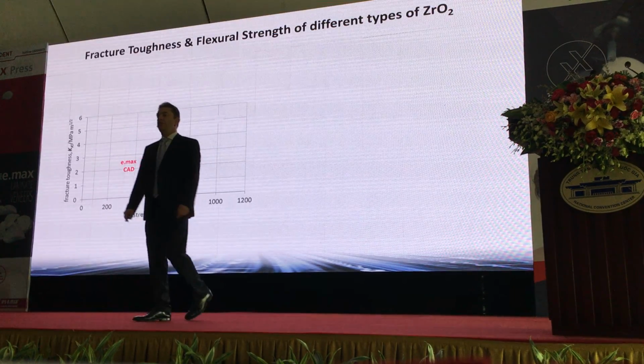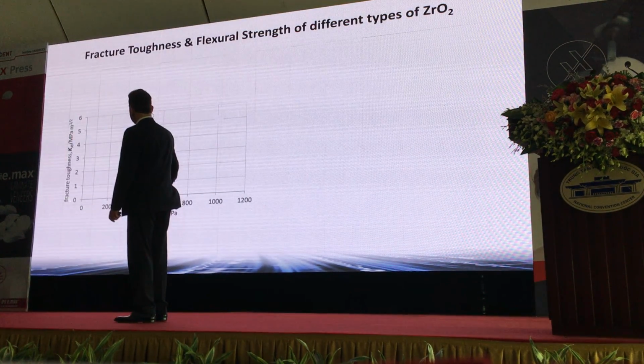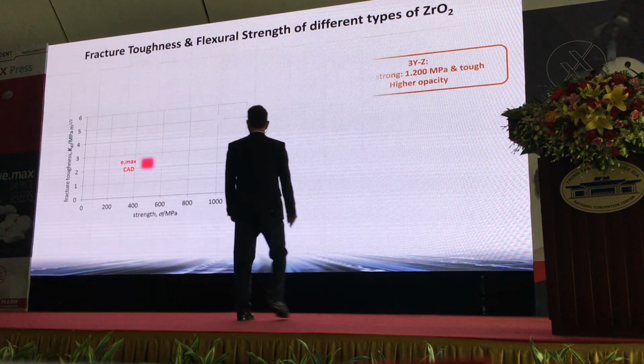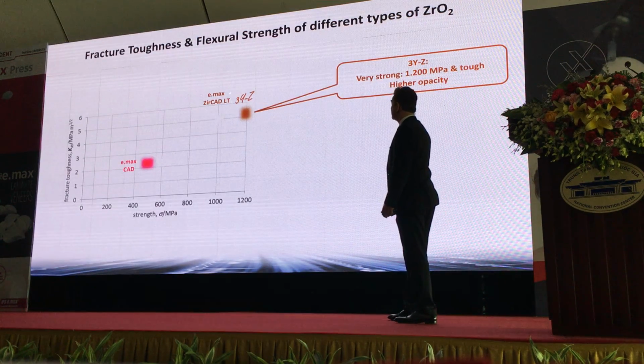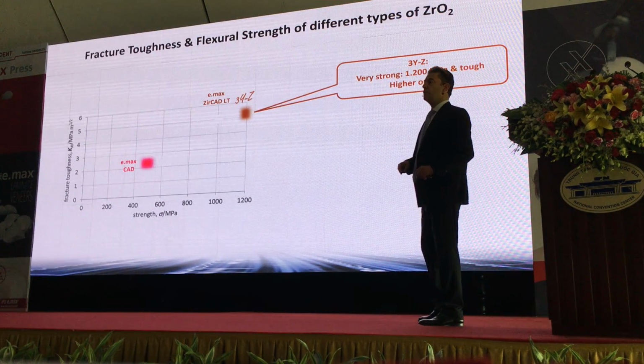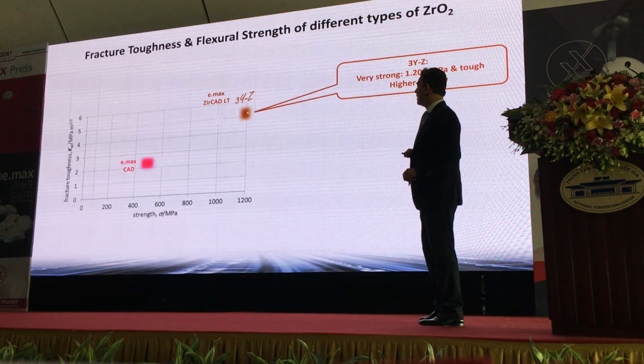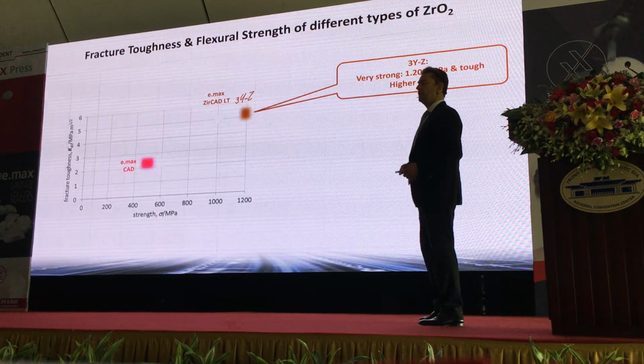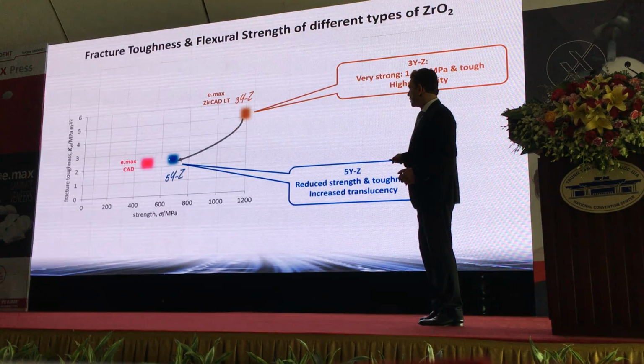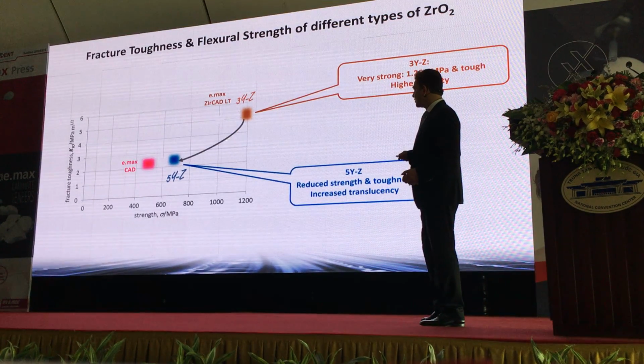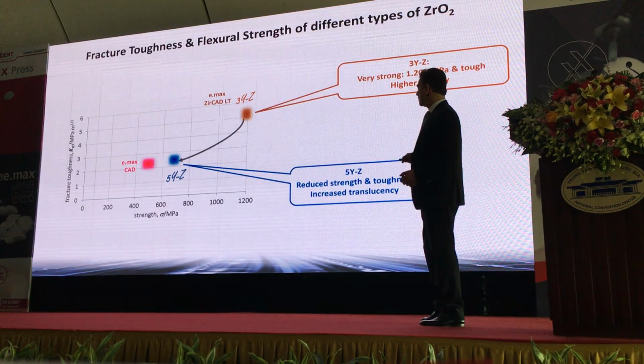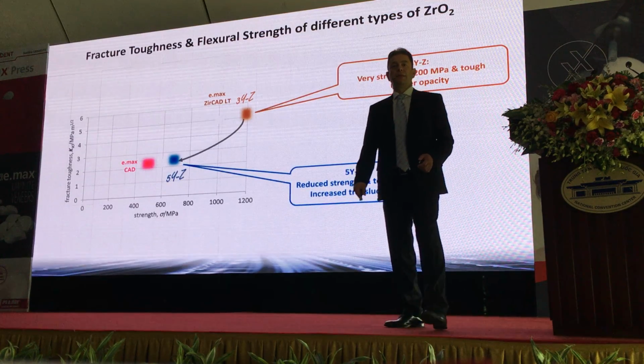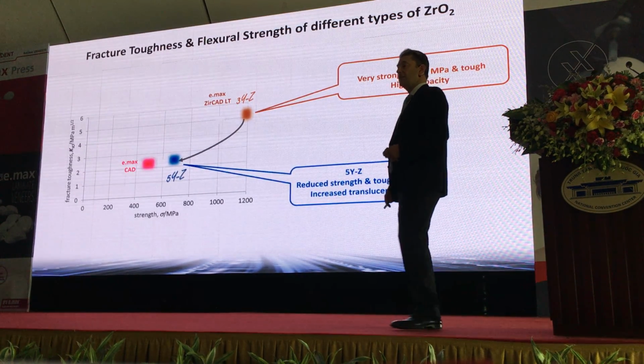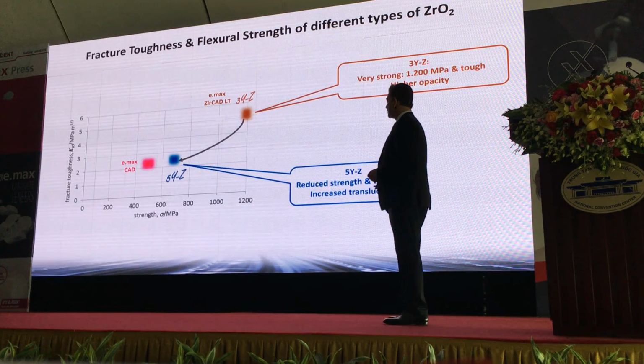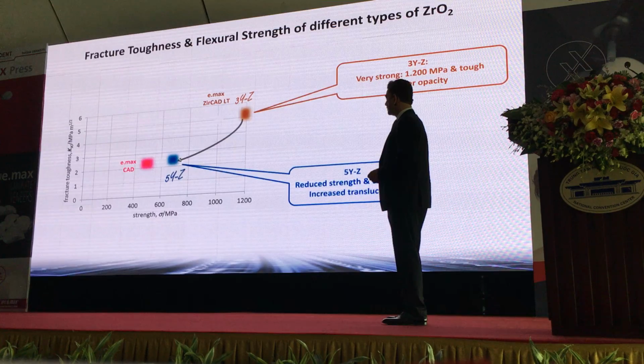All right, and you can see if we compare now the different zirconia to Emax, the original Emax lithium disilicate, we see this fracture toughness and flexural strength. So up here, this is the original, let's say, zirconia, the very strong zirconia, which is more opaque. So we have the very high flexural strength and fracture toughness. And if we really put a lot of yttrium oxide, much more than this one, the physical properties are decreasing. You can see, not so different from Emax. So these are the most translucent zirconia that are in the market, 5YZ zirconia. More translucent, but regarding strength, not so much difference now to the Emax.